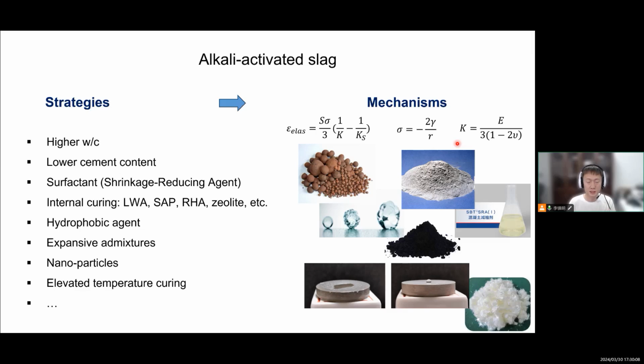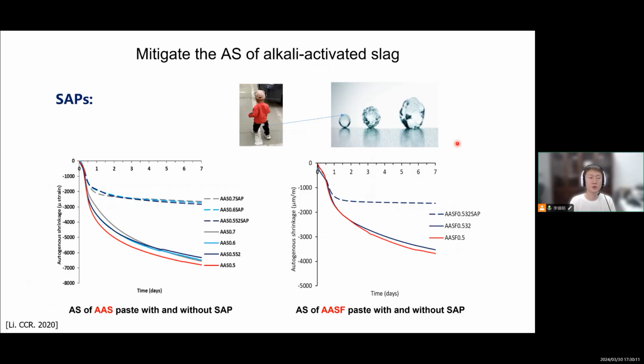So I basically consider two methods, one is internal curing by the superabsorbent polymers, which are actually not new. They were already used in Portland cement for a long time, so I just use it. I didn't propose it. We can see that it worked. It reduced the shrinkage by more than half, basically in the later age. In the early age, the SAP cannot really eliminate the shrinkage, which is quite reasonable because we already said the self-desiccation is not its own mechanism. So however big an amount of SAP I add, even more than needed, the shrinkage is still there, especially in the early age. So we cannot fully mitigate the shrinkage, but it worked really well in the later age.